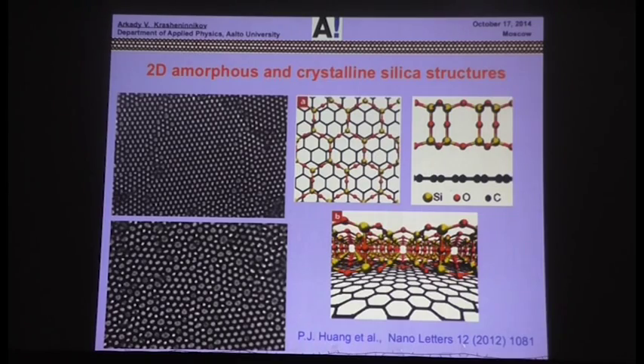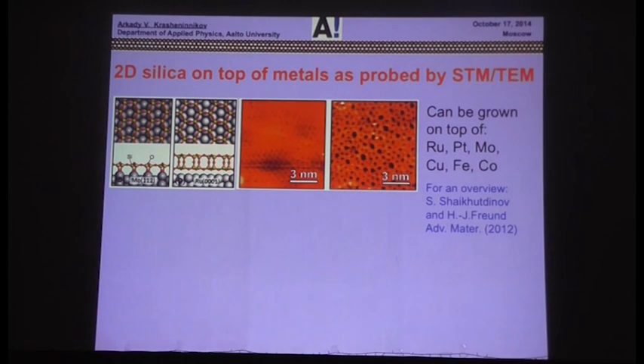Actually, in our calculations, I go back, we work out the most stable structure, and later on, as you know, in Russian there's an expression "to invent a bicycle", basically to do independently something that has been known before, but you were not aware of. We realized that actually the Berlin group had grown similar structures, epitaxial SiO2 and silica bilayers, van der Waals interaction on different metals for quite some time. In our case, copper was essentially dissolved and the structure was moved to a TEM grid.